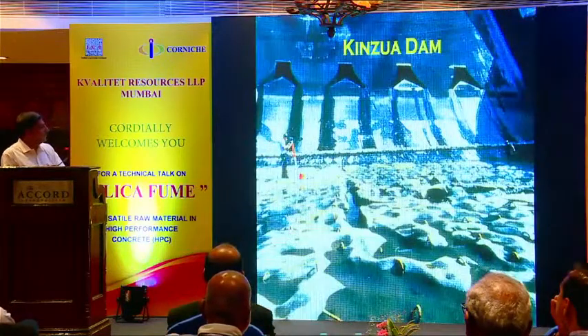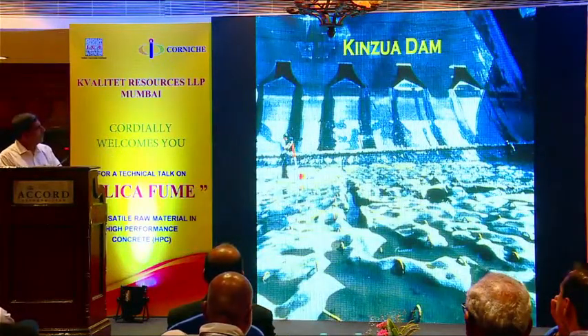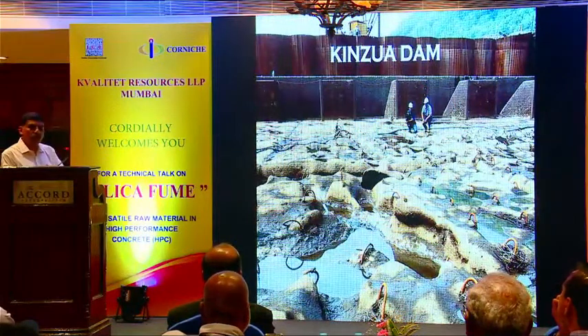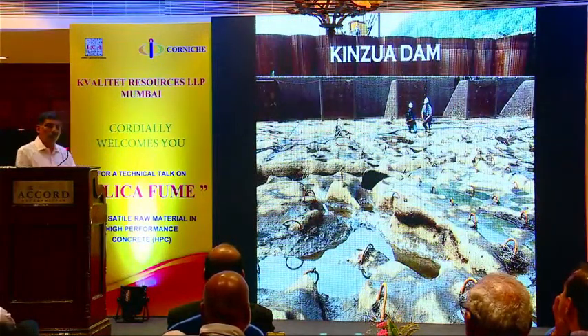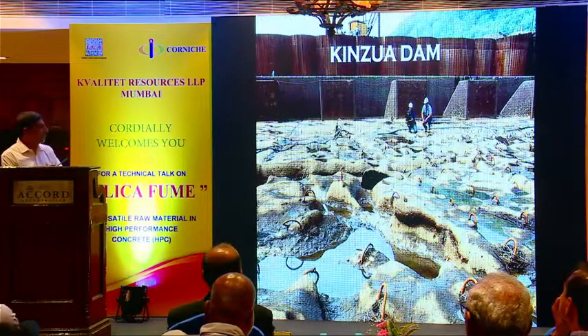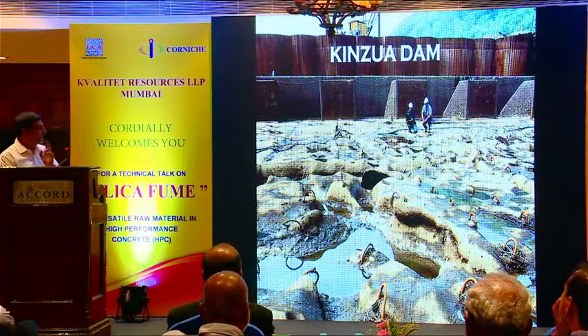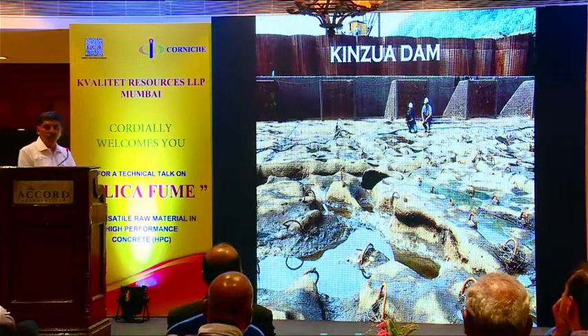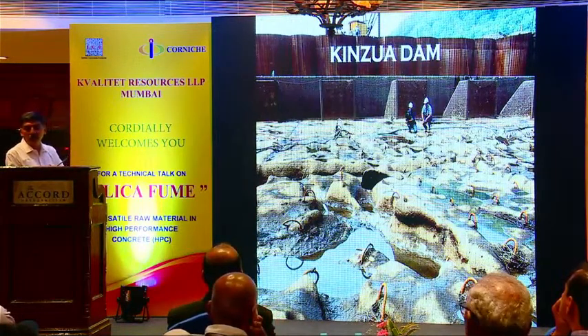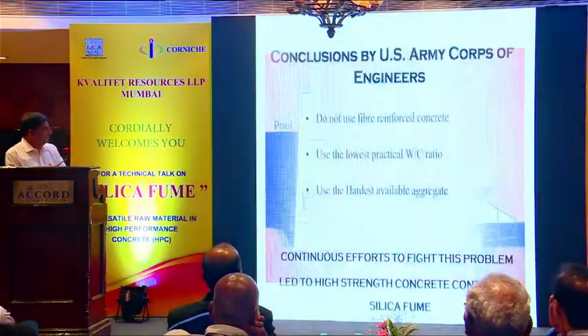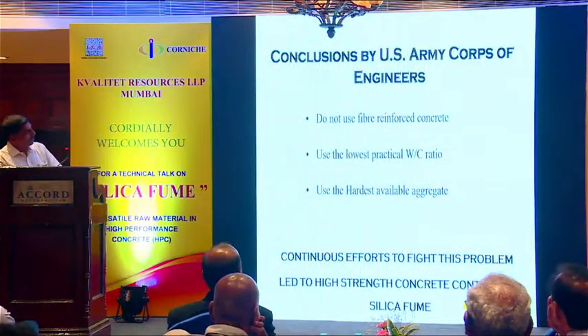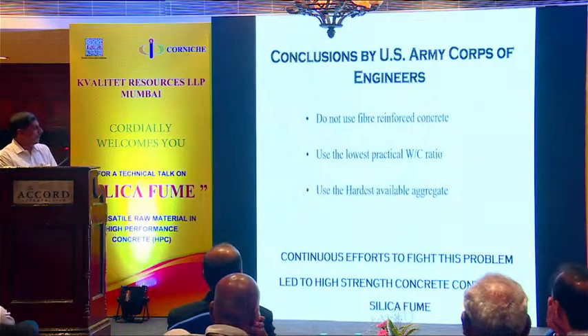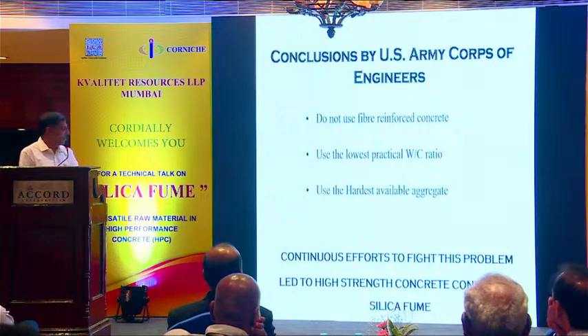Then I think this is what it was looking like. The wise heads put their heads together, did various trials. They came to a conclusion for silica fume concrete. The second repair was done in 85 to 87. It's still standing. So conclusions: do not use fiber reinforced concrete, use the lowest possible water cement ratio, use the hardest available aggregate. Continuous efforts to fight this problem led to high strength concrete containing silica fume.